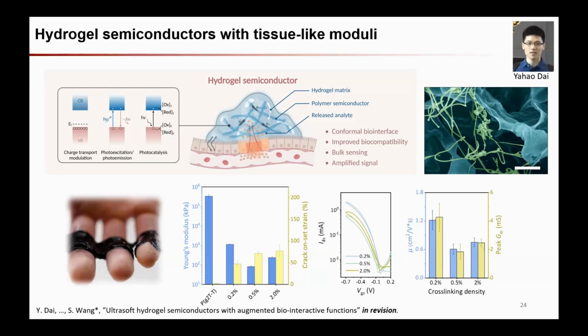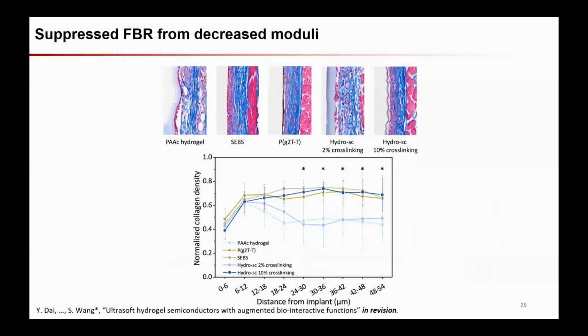With the semiconducting polymer, you can see from this SEM image, forming a nanofiber, highly porous structure embedded in another porous structure of a polyacrylic acid hydrogel. On one hand, that led us to decrease the Young's modulus compared to the neat semiconducting polymer by about 2 orders of magnitude. At the same time, for the electrical performance in transistors, it didn't really sacrifice the charge carrier mobility.